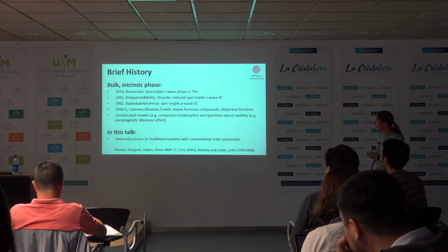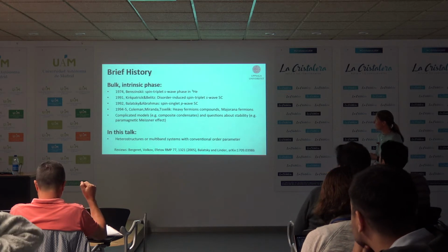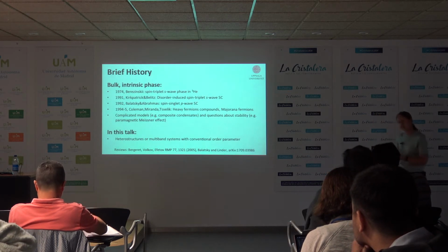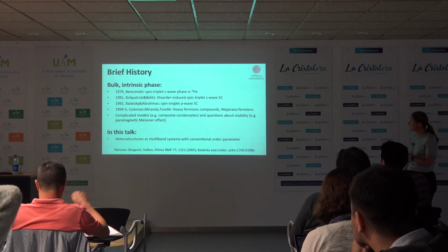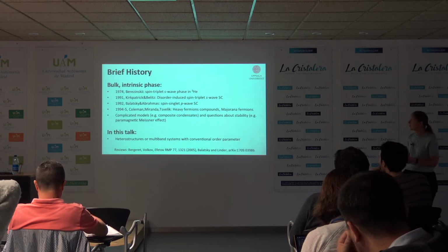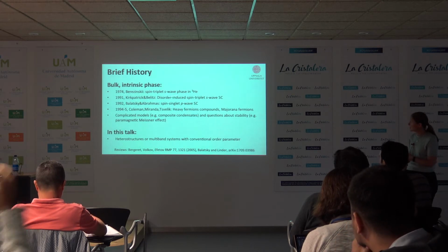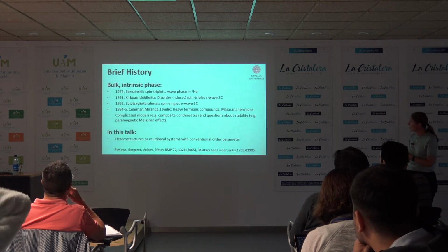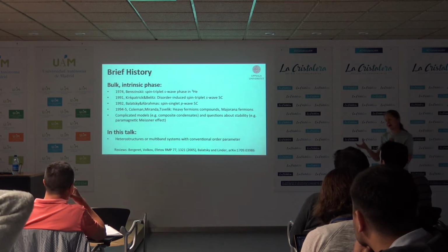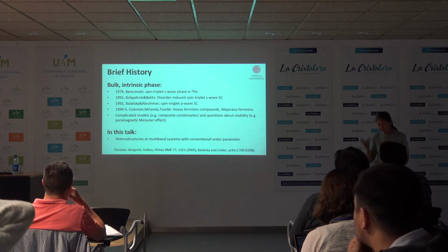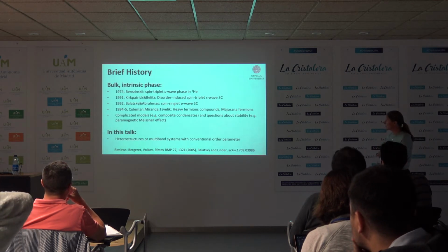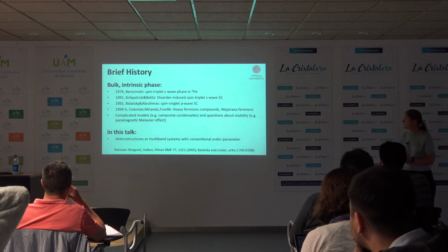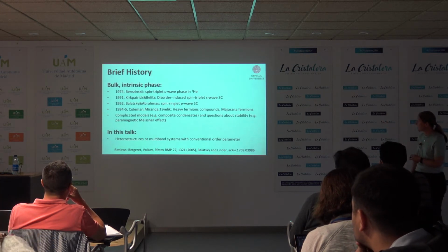This presumably was rather dormant for a while, and then in the early 90s, several people picked this up for superconductors, proposing a spin triplet S-wave superconductor that was disorder induced. And here it is exactly disorder induced, because if you have disorder, then you presumably will only have S-wave. The other spatial parities will average out to 0. And if you then want it to be spin triplet, that has to be odd in frequency. Later, spin singlet P-wave odd in frequency was also proposed.